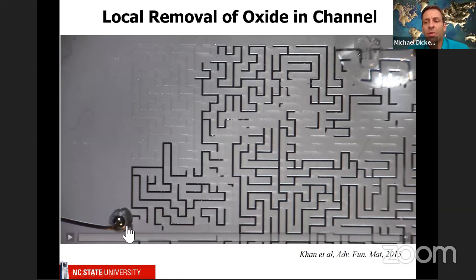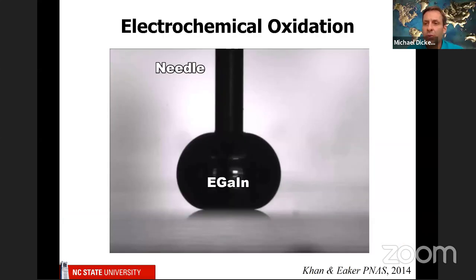And naively, you might think, well, instead of applying -1 volts, which is how we remove the oxide, what if you apply +1 volt? The problem with that is that if you use positive voltage, you're just going to deposit oxide on the surface and it shouldn't do anything. So you can imagine how surprised we were when we did this experiment.